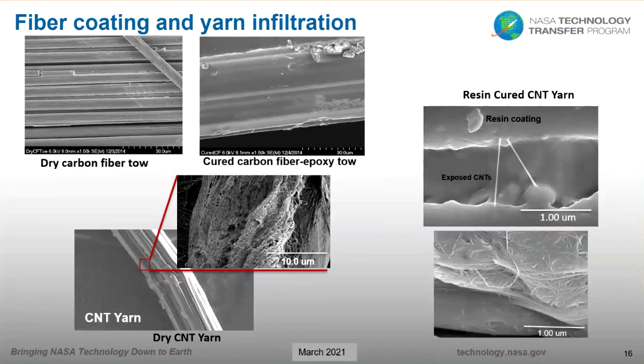So from our work, the good thing is that we did not observe an immediate knockdown in the tensile properties after making the hybrid tow. And one reason why this is the case, I believe, is related to the unique architecture of the carbon nanotube yarn compared to the carbon fiber. When you make a composite made of carbon fiber or any other fiber like glass fiber, boron, or aramid fiber, you are basically coating resin onto the filaments, like what I'm showing in this micrograph. And so you are relying on chemical interactions between the resin and the surface properties of the fiber to provide you with ideal interfacial bonding.